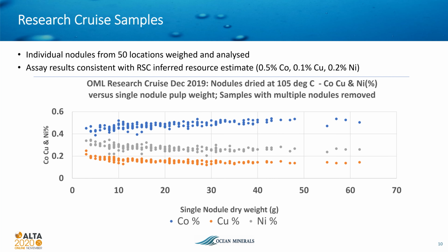One of the OML geologists suggested that this difference in assays with nodule weight may have been due to nickel and copper grades being influenced by the underlying sediment, while the cobalt assays could be influenced by the ocean waters. So the larger nodules would have higher cobalt but lower nickel and copper.